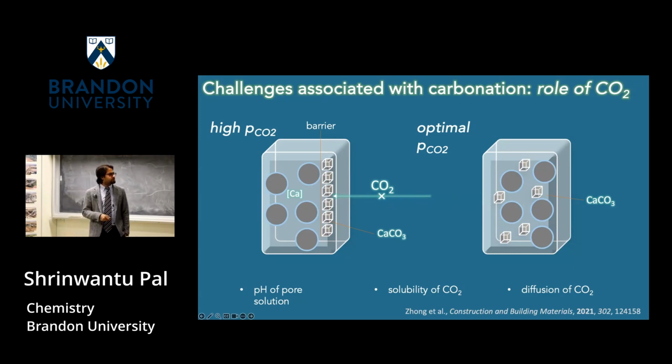So at that time, I was just playing around with finding out the pH of pore solution. So every day I would get covered, well, secondary effect, but primary is I would take buckets of slag and place them together and pour water in it and then let that sit for a while and with Pasteur pipettes microscopically take out the water between the two particles and check for the pH. Once we figured that out, we did some rudimentary modeling of the pH solution, and we found that there was a very good dependence of the pH on how far deep into the sample you're going.